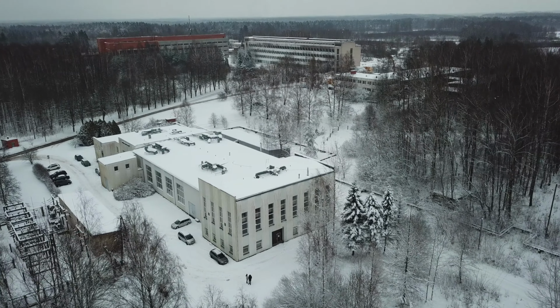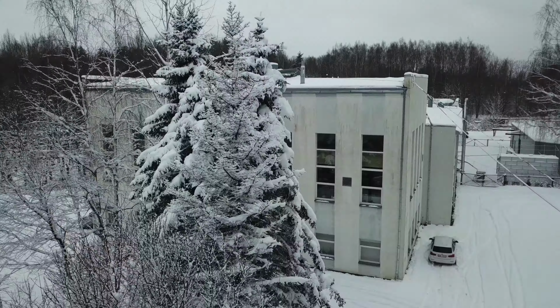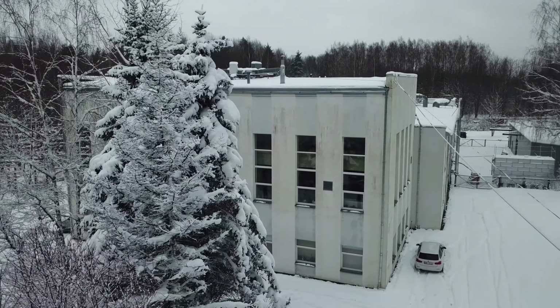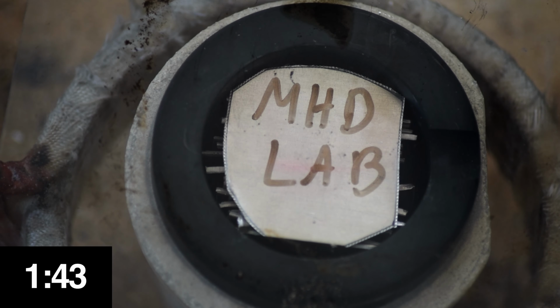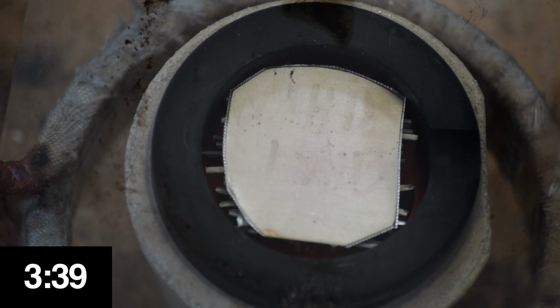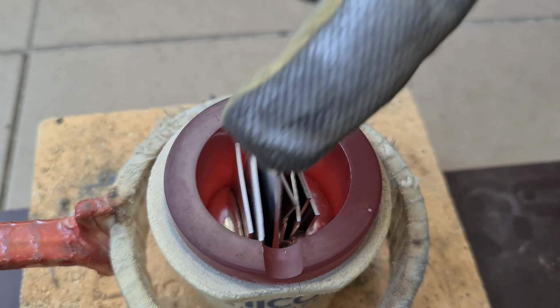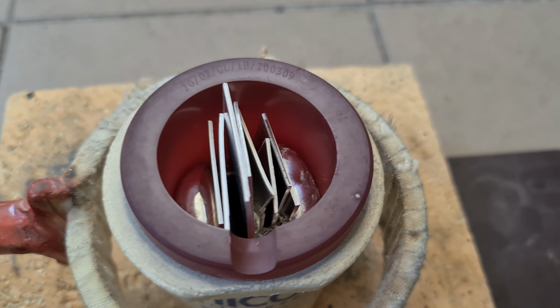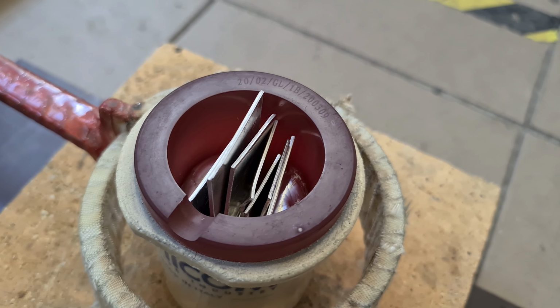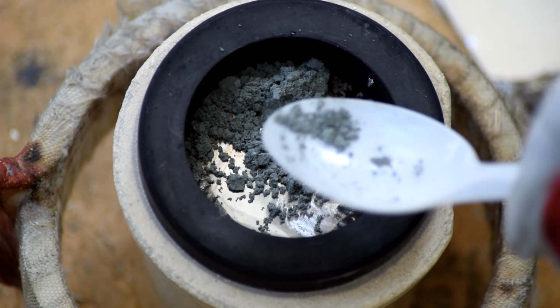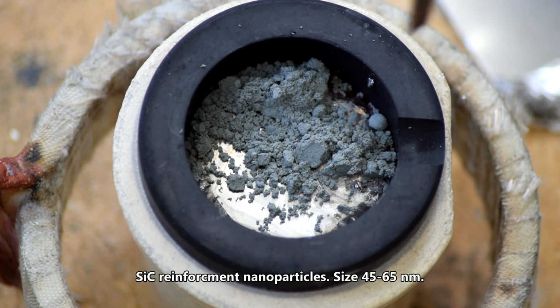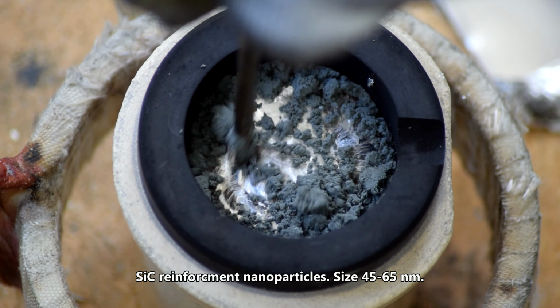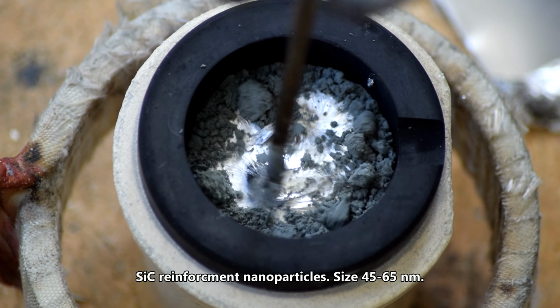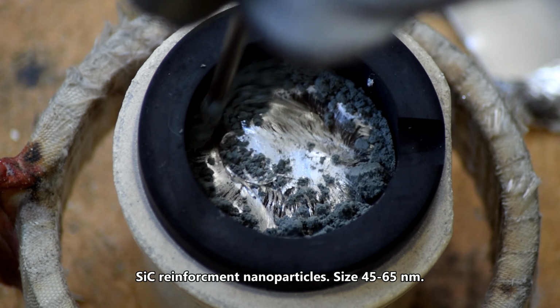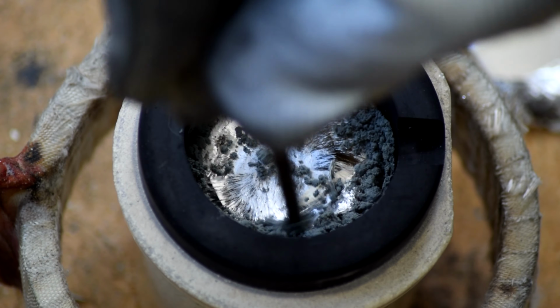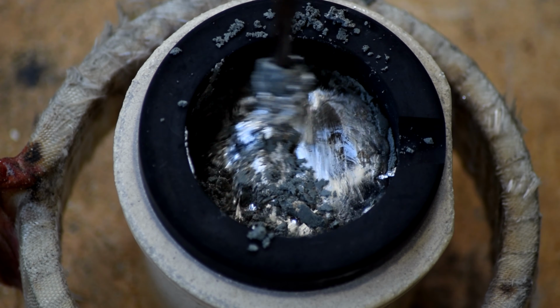Let's move to the Institute of Physics, where we can do experiments with molten aluminum. We start by taking aluminum alloy and melting it using an induction heater. Rapidly changing magnetic fields melt aluminum contactlessly, and when it's fully melted, we add nanoparticles. These silicon carbide reinforcement particles are tiny, measuring only 50 nanometers. To make a high-performance aluminum alloy, you want these particles to be homogeneously dispersed. Only then do they improve the mechanical properties of the alloy.